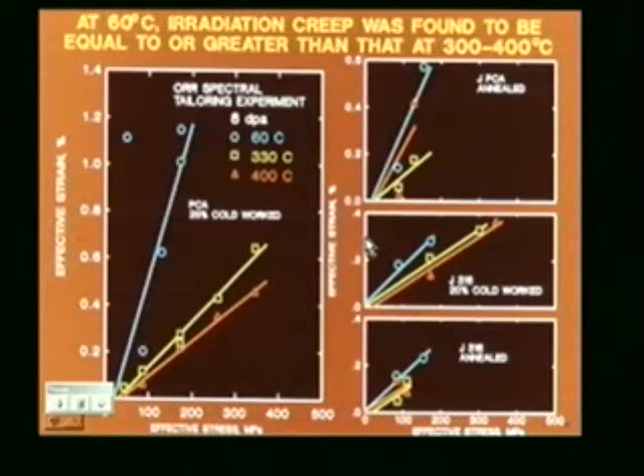Well, I didn't say much about temperature in this case. Here we have some irradiation creep results from, in this case, the High Flux Isotope Reactor. And here we see strain as a function of stress, plots for 300 and 400 degrees, and now we see another plot for 60 degrees where it's even higher. So we kind of mislead people even when we call it creep, because it's not a high temperature phenomenon, it's an irradiation phenomenon.